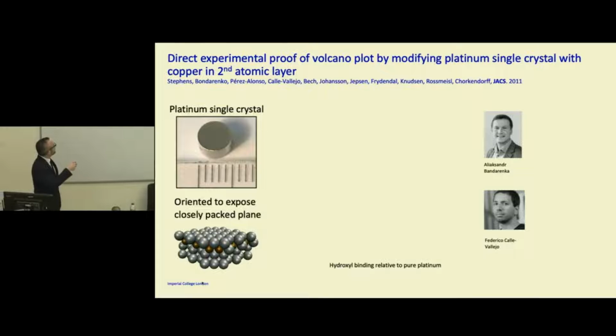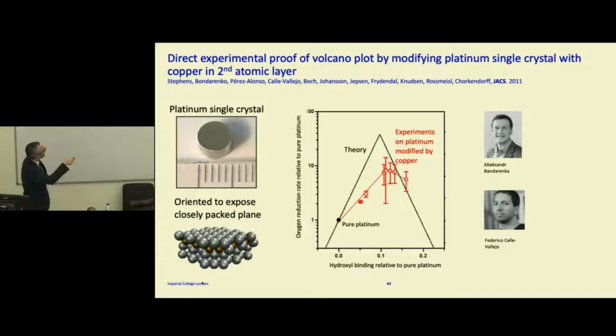And what we found was some theoretical studies saying if you put a little bit of copper in the very surface layer, you should be able to weaken the binding of platinum to reactive intermediates. And we thought if we could change the amount of copper, we could try and map out the volcano. And this is what we did. This is the theoretical prediction. This is the experimental result. We didn't quite reach the maximum predicted by theory, but this is to be expected. This is as good as we could possibly hope for in agreement between experiments and theory. So this is really exciting for us to work on.